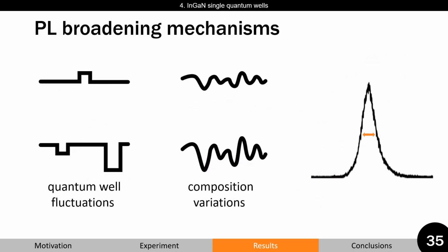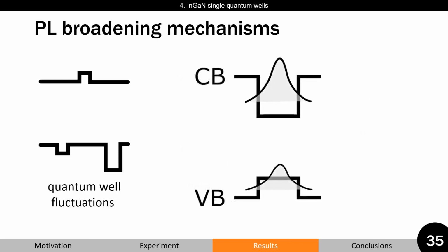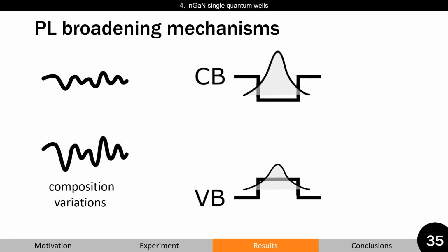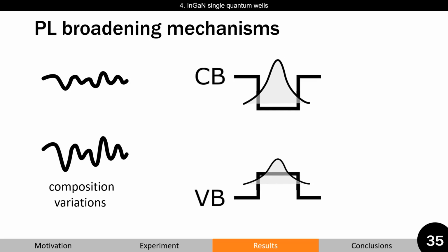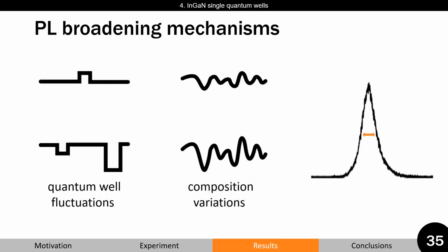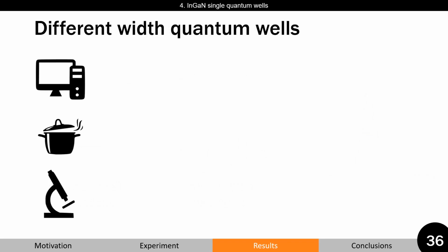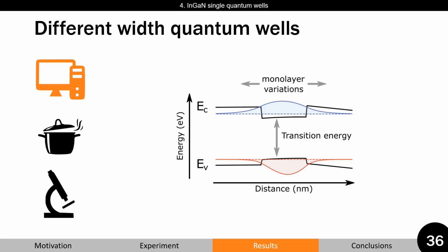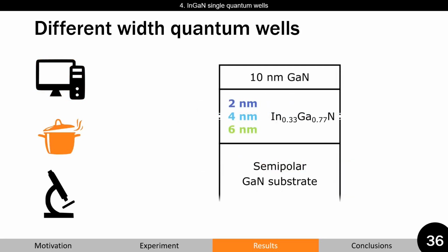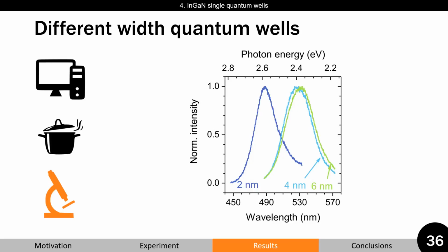Finally, I would like to return to photoluminescence in the case of single quantum wells. Because this is a more complicated structure, we can no longer avoid quantum well width variations, which do affect the transition energy. In addition, composition variations would also lead to variations in transition energies. Therefore, when people are studying quantum wells, photoluminescence broadening is usually attributed to these two processes. We again decided to try to differentiate them by conducting a simple experiment. First, we modeled transition energy variations by few monolayer fluctuations. Then, samples were grown at University of California, Santa Barbara with the same indium content but different quantum well width. Finally, samples were measured here at KTH using scanning near-field optical microscopy.